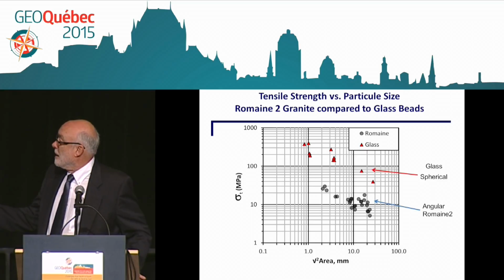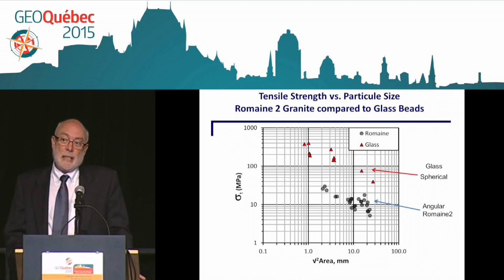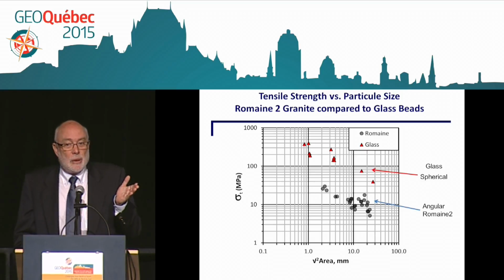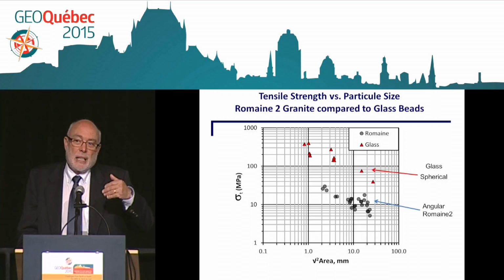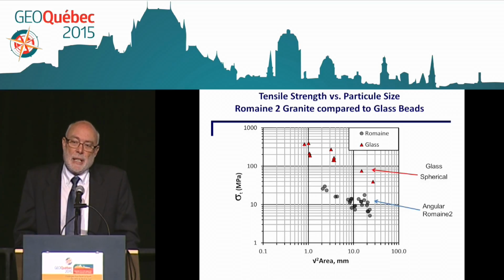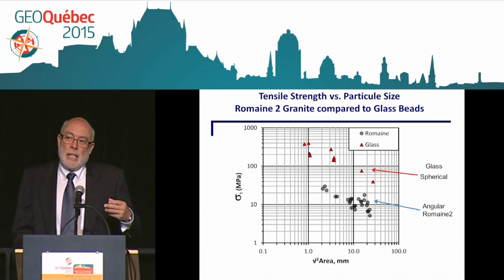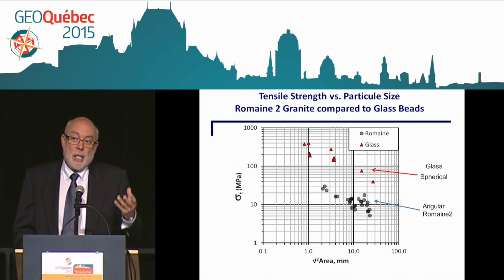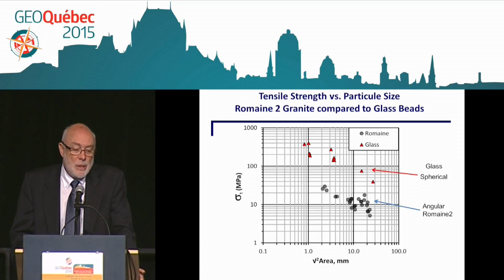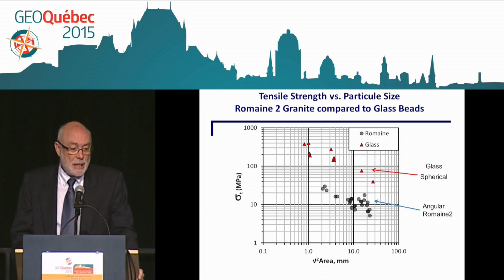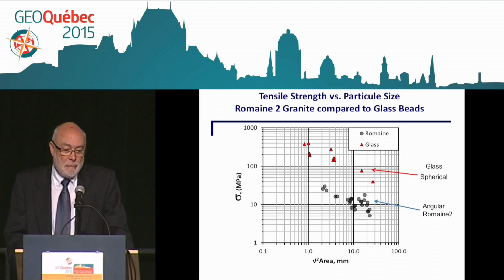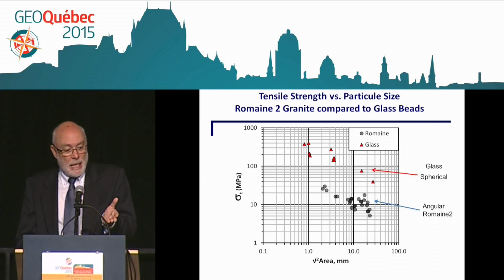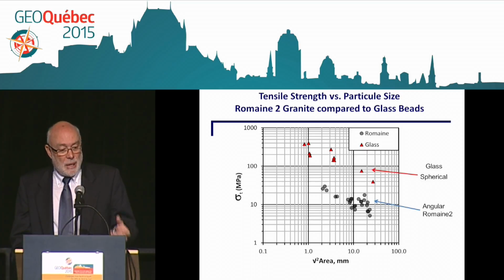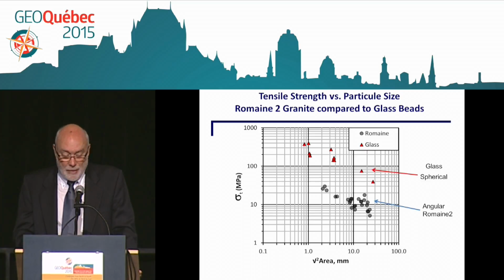And this is making sense since the breakage is really related to a phenomenon called crack propagation failure, a fracture mechanism failure. And you see the defects would increase in particles with increasing size. So it's somehow intuitive that the strength would decrease with increasing size of the particle. It's also interesting to compare glass beads to angular Romaine 2 material. We see the glass beads are stronger, and this is due to the shape. So keep that in mind, please. But even for glass beads, the larger the glass beads are, the less strength we have.